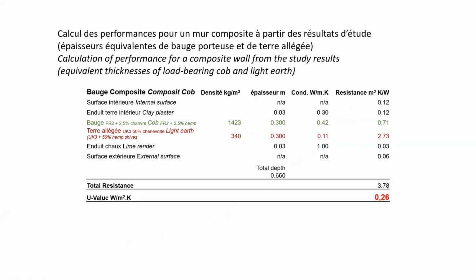But these different curves and graphs helped us simulate the thermal behavior of a composite wall. So we thought about the relationship and the performance that we could get with this combination of mixes, a thicker load-bearing cob and light earth, with different thicknesses. So here we had two mixes that were combined: a load-bearing dense cob mix of a density of 1.4 and the light earth mix of a density of 340 kilograms per cubic meter. And both of these were 300 millimeters wide.